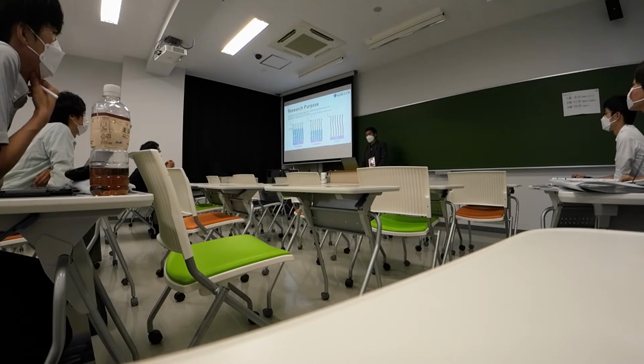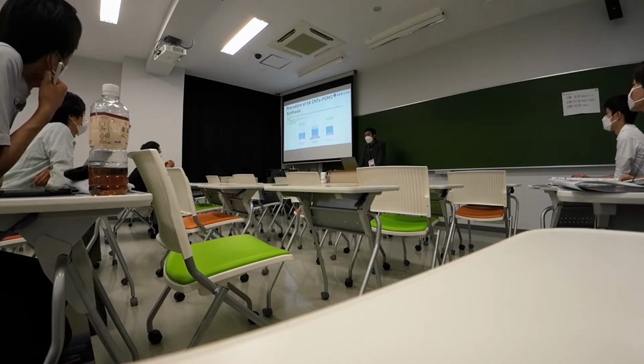We have three samples. First, composite with higher PDMS, second with lower PDMS, and VACNT only without any PDMS. The hypothesis is that the higher PDMS thickness will increase the lateral stiffness of the VACNT surface. Here is the procedure. We present a novel method where the fabrication occurs on PDMS liquid with rapid curing, which keeps the PDMS elasticity. These are the 3D stages.